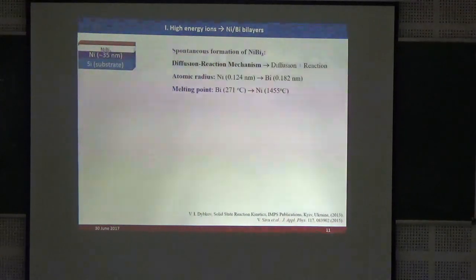What happens is, whenever bismuth is depositing on nickel, the atoms of bismuth at the interface will diffuse into nickel at first, and then react with nickel. That is why it is called a diffusion reaction mechanism. There are two possibilities for that diffusion process: either nickel will diffuse into bismuth or bismuth will diffuse into nickel. One would expect, due to the smaller atomic radius of nickel, that nickel will diffuse into bismuth. But it is the other way around, because bismuth is a very volatile material and its melting point is very low. Due to this large temperature difference, the second one is the most likely, which was proposed in this book.